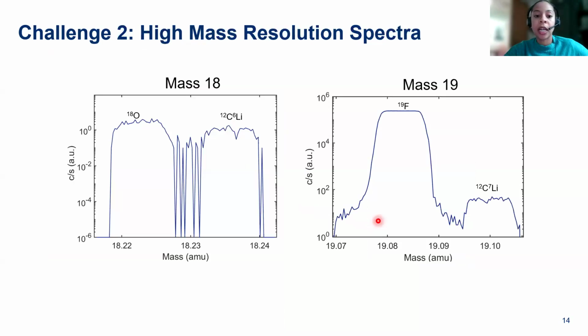So the second challenge that I had to address was because there isn't very much literature on the NanoSIMS analysis of lithium-ion battery materials, I had to build up my own library of mass spectra. So here I show some examples of high mass resolution spectra at mass 18 and mass 19. So at mass 18, we see a very clearly resolved 18O peak and a very clearly resolved 12C 6 lithium peak with very little overlap between the two peaks. And at mass 19, you see something very similar, a very clearly separated 19F, so a fluorine peak separated from a 12C 7 lithium peak. And we're also really surprised that we're able to see any lithium peaks with such good resolution and good intensity using the cesium beam.